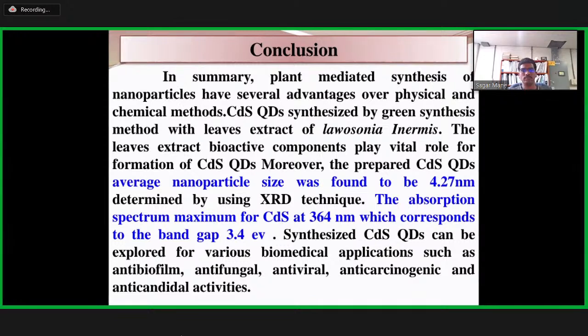The prepared CdS quantum dots' average nanoparticle size was found to be 4.27 nanometer, determined by the XRD technique, and the absorption spectrum maximum for the CdS is 364 nanometer, which corresponds to a band gap of 3.4 electron volt. Synthesized CdS quantum dots can be explored for various biomedical applications such as antibiofilm, antifungal, antiviral, anticarcinogenic and anticandidal activities, etc.